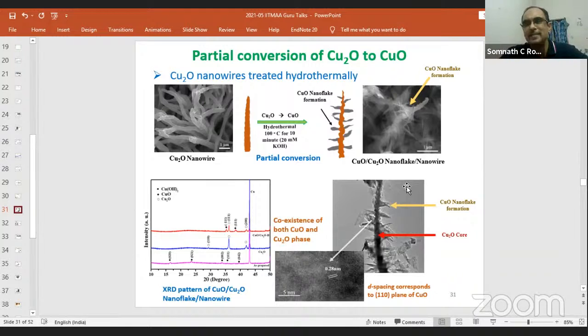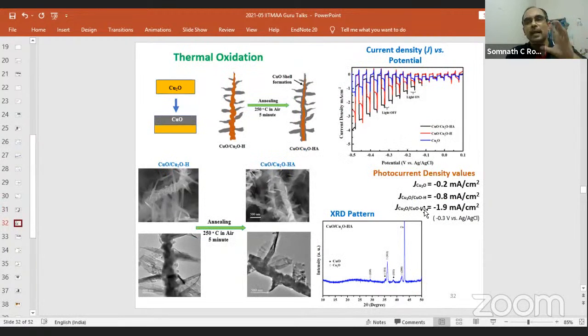Nature is so beautiful that it creates such structures for us. All we have to do is to put the right ingredient, the right temperature, the right ambience at some vessel, and the nature will do it. Well, we are trying to understand this more, but this is another beautiful work that we have done. We have produced this, or I can call it also cactus type. My student did not like this word cactus. This center portion is Cu2O, and the flakes which are coming perpendicularly are actually CuO. Again, we have found that the photocurrent generated under light, electrochemical photocurrent, had 1 order of magnitude increase when we had this kind of structure.